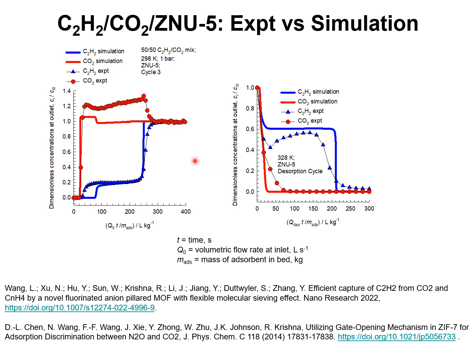The message that emerges from these comparisons is that for flexible MOFs, strong isotherm inflections are reflected in IAST calculations of mixture adsorption selectivity and component breakthroughs, with the component breakthroughs showing stepwise behavior. A completely analogous situation holds for separations of mixtures of nitrous oxide and carbon dioxide in flexible ZIF-7, and I invite you to examine this paper published in the Journal of Physical Chemistry in 2014.